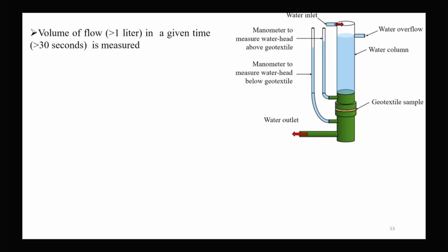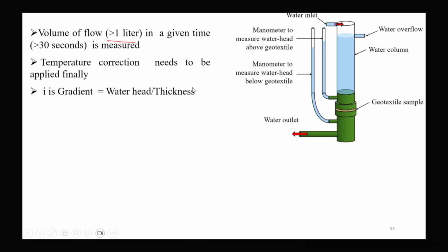The volume flow rate is measured for more than 1 liter in a given time, which is more than 30 seconds. Temperature correction needs to be applied.